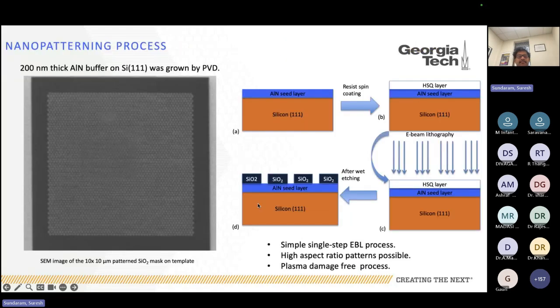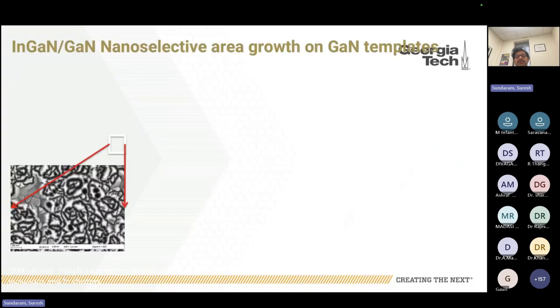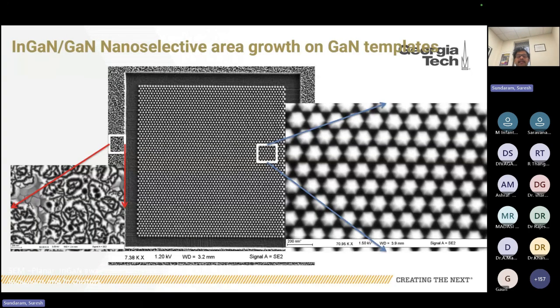So this is the mask or the pattern that is transferred onto the silicon and aluminum nitride layers. You can see the entire mask or pattern size is 10 micron by 10 micron. Each hole opening is less than 100 nanometer. To be precise, the opening size is 60 to 80 nanometer. We take this patterned substrate and realize growth on top of it. You can see it clearly here.